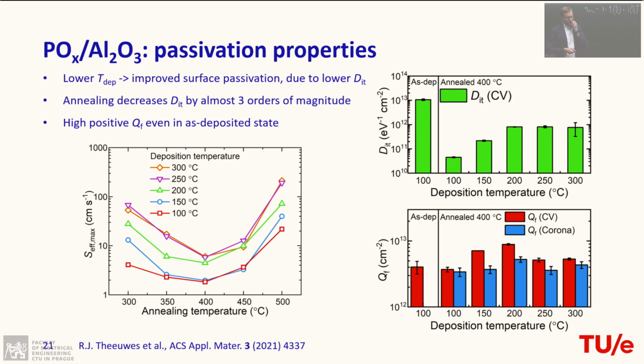Then, is it possible to understand how this actually works? If we express it again in terms of this interface defect density and fixed charge density, and we grow our stack at different temperatures, you see interesting trends. For lower deposition temperatures, you see that my surface passivation is improving. You see this trend over here. So your DIT is really reducing by orders of magnitude if you do this. And if you anneal, as you can see over here, you see also that your passivation quality, now expressed in effective surface recombination velocity, is also improving. So by using both the growth temperature and annealing temperature, you can manipulate it.